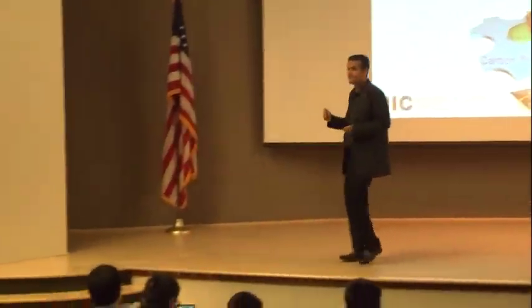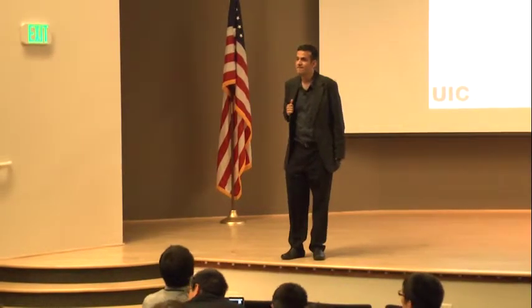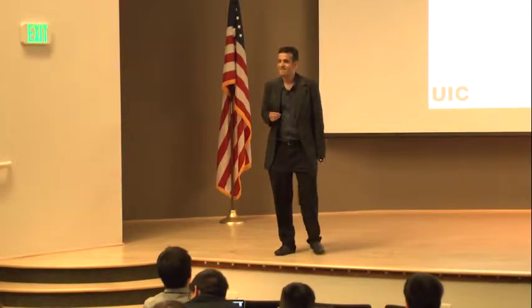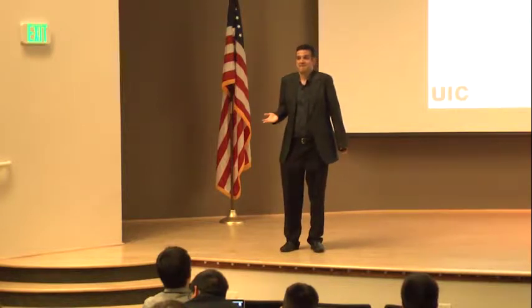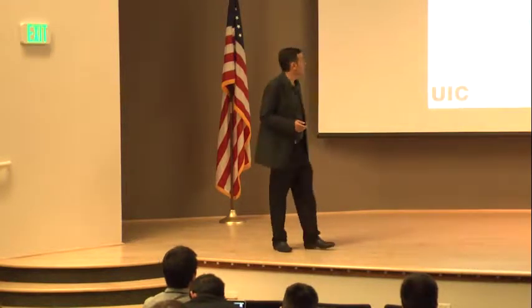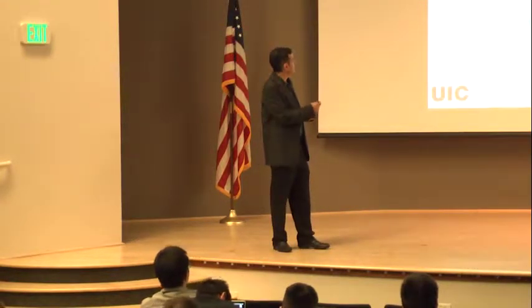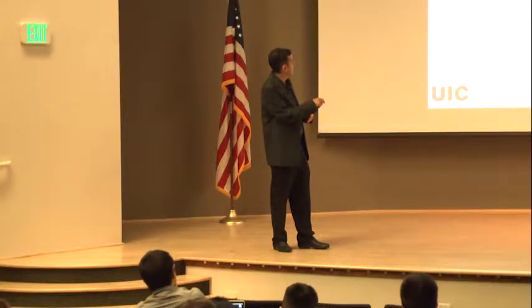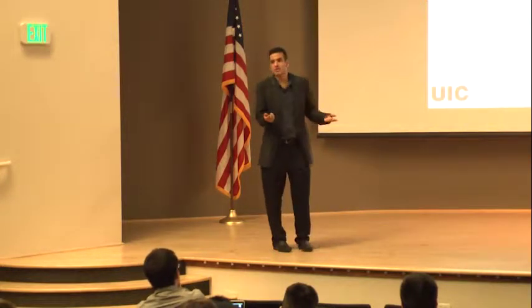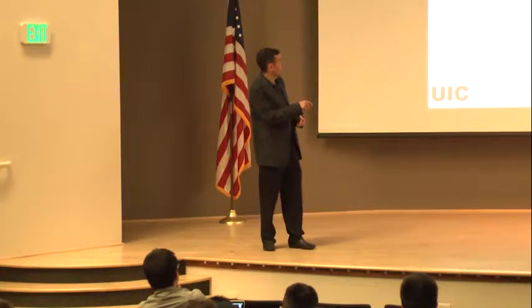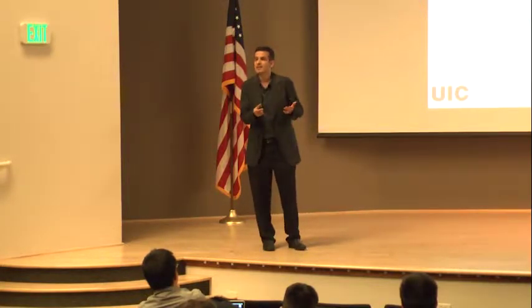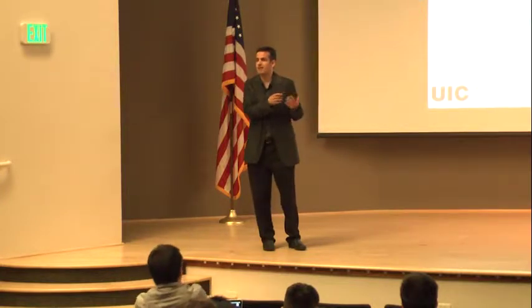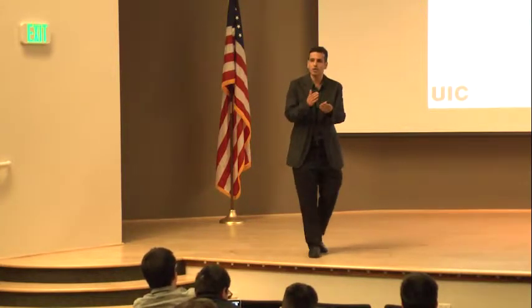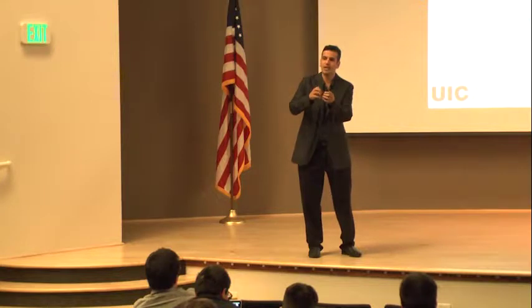Following along with that question, what happens to the strain or the defects in that particular particle, even over a short period of time? That's quite a bit of strain. Does it start cracking more? Well, do you see any evidence of that? This particle already had a crack here. And the question is, what's first, the chicken or the egg? Did this domain end up here because of the crack, or did the crack end up there because of the domain? And the previous snapshot doesn't tell you that, right? We don't have quite the time resolution to really see this domain appearing and growing.